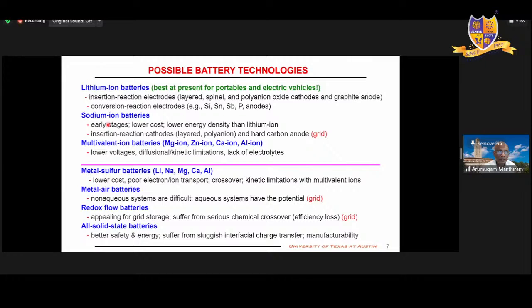So that's not good. So we have been controlling all these parameters as you see here: low carbon amount, high sulfur loading, low liquid electrolyte, and low amount of lithium. We call it 5.5. Also, we do pouch cell. If you do button cell with lithium sulfur, it will not be realistic. It will not tell you everything. So we do pouch cell. And then we have done a lot of fundamental work to understand what is really going on.